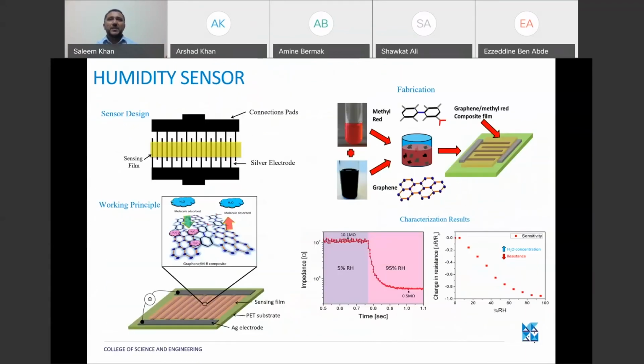Similarly, the humidity sensor, as we have seen in the previous slides, uses interdigital electrodes, and you can see the sensing layer. It works on the conductivity change. The methyl red solution is used, and we tune the conductivity when water molecules are deposited in the sensing layer. Here we can see the fabrication steps, and all these are developed using printing technology. The interdigital electrodes are developed using inkjet technology, and a casting technique is adopted for deposition of this methyl red solution. Here we can see the characterization results for the sensitivity and the impedance response of the sensor.